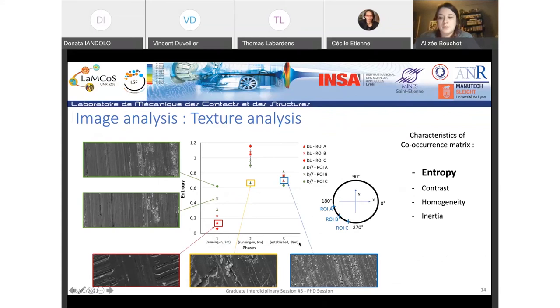In the case presented here, we have two disks with different initial surface conditions. We were able to note that the contact would evolve differently in both cases to find themselves in a similar situation once the stationary regime was reached. Here we see the different states of entropy at the beginning because the texture was very different. There is a smooth texture here for the red disk, and there are a lot of particles on the green one.